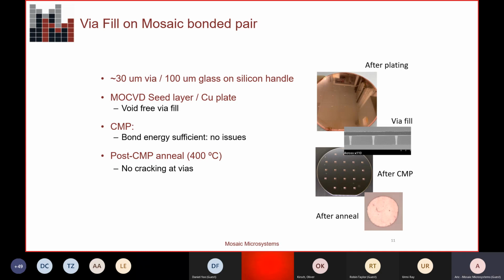If you have voids in those vias, that's actually been the reason for a lot of failures in previous work in glass. If you don't do the via fill properly and you have voids and you raise the temperature, the voids in that copper expand much more than the glass or the metal, and that causes cracking. By avoiding the voids, I've done quite a bit of work with ITRI and Georgia Tech and Micros. If you avoid the voids, you can get very good reliability. We've passed HASS testing, thermal cycle testing, and drop testing, but it's really important to not have voids in that copper. And again, by mimicking TSV type vias, you really improve your ability to avoid those voids.